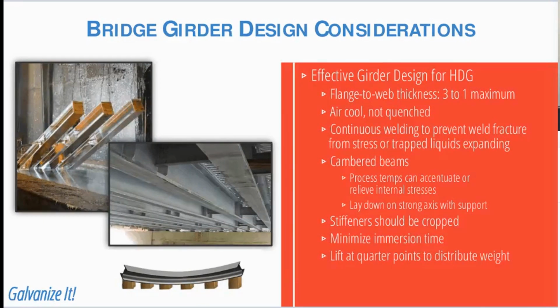Meanwhile, when it comes specifically to girder design, there are some key industry best practices that can help maximize quality and avoid warpage. First is to ensure any flange to web thickness ratios are no more than 3:1 in order to avoid distortion of the web. The finished galvanized girder should also be air-cooled instead of quench-cooled after galvanizing in order to minimize additional induced stresses from cooling.